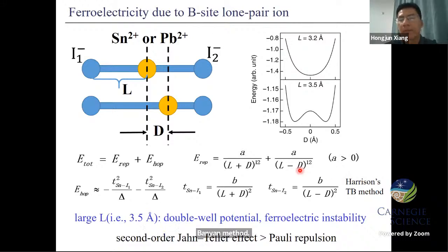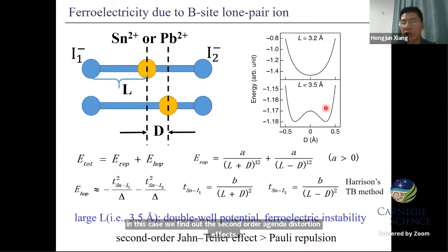So we found that if the distance between the center and the ion is small, then the lone pair would like to stay in the center, so there's no ferroelectricity. However, if the distance is large, then it will displace from the center symmetry position to the ferroelectric state. In this case, the second-order Jahn–Teller effect is stronger than the Pauli repulsion, so this will give rise to the ferroelectricity.